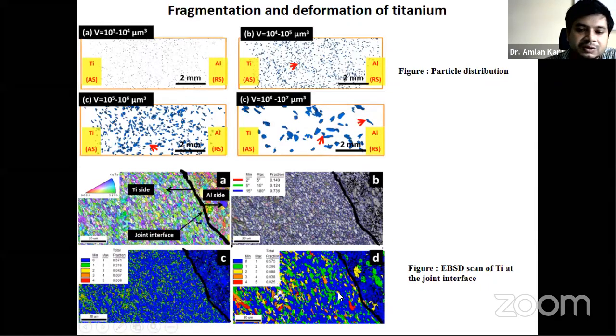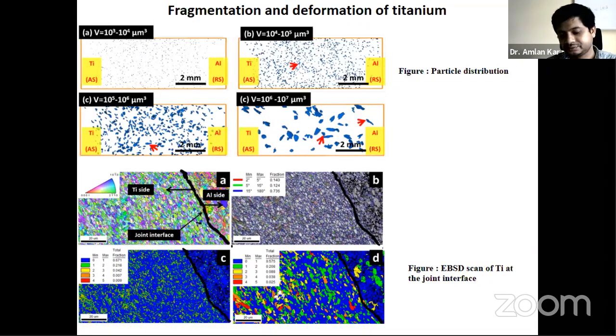And even from the GOS map, which defines the recrystallized grains, where the blue with orientation deviation from 0 to 2 is called the recrystallized grain, we can see there is recrystallization. A huge number of recrystallized grains is present over here. So this is sort of recrystallization taking place, which is quite an unusual phenomenon in the case of titanium subjected to high strain deformations at low temperatures.